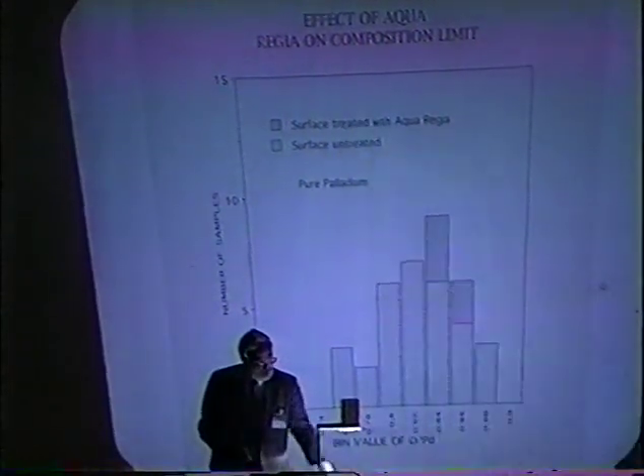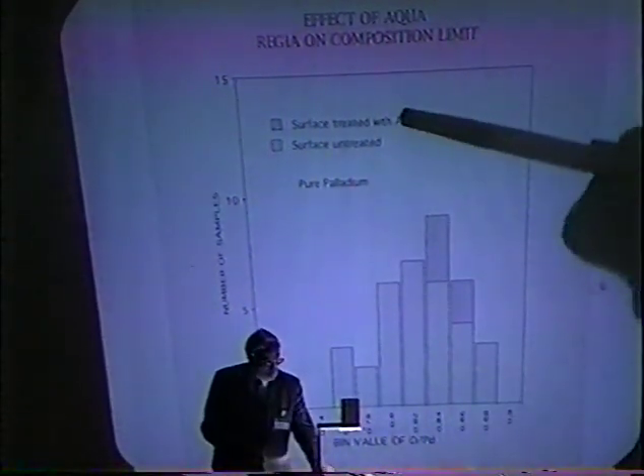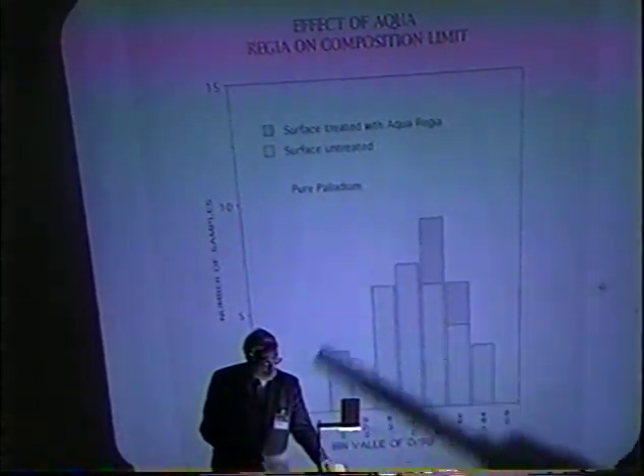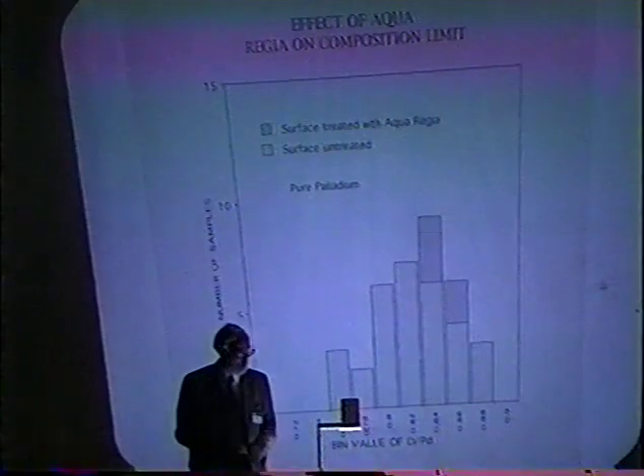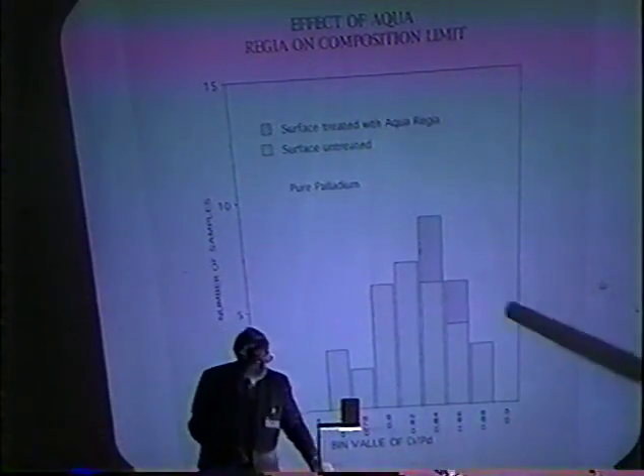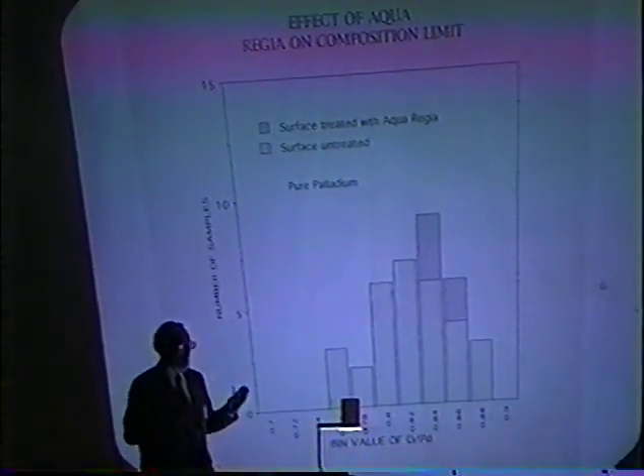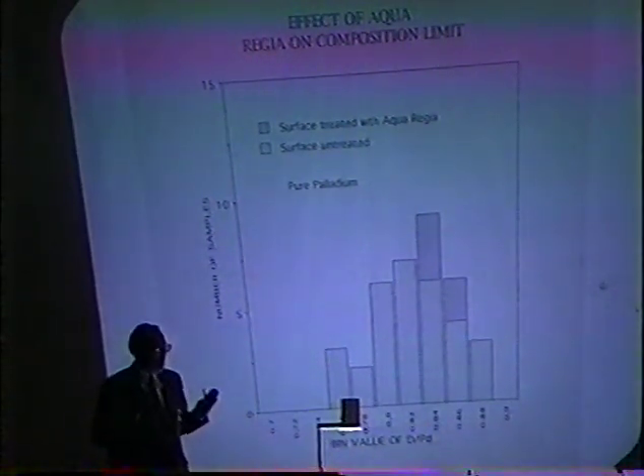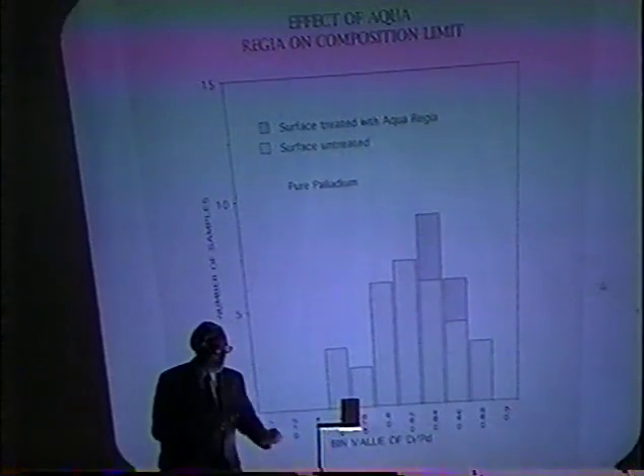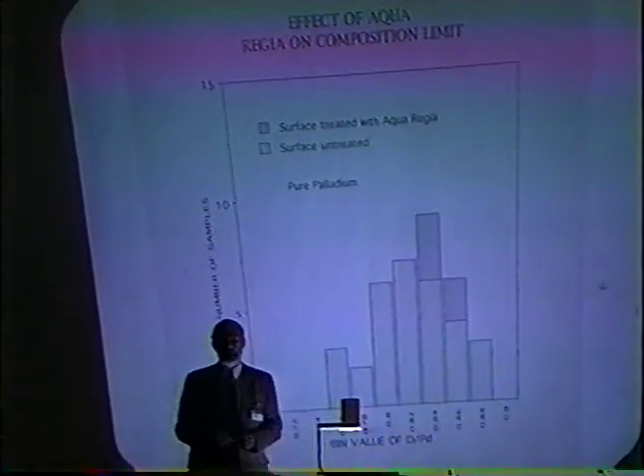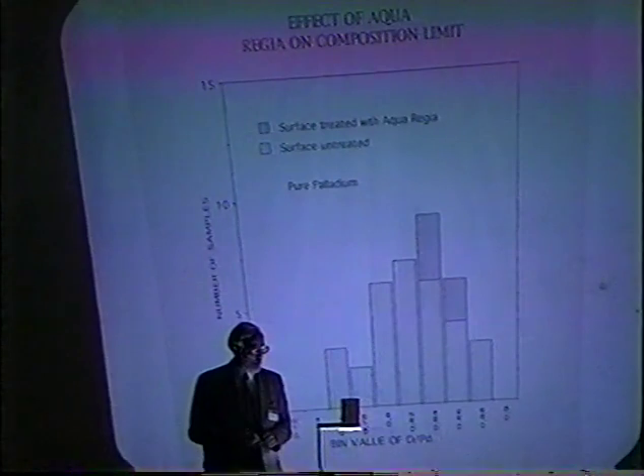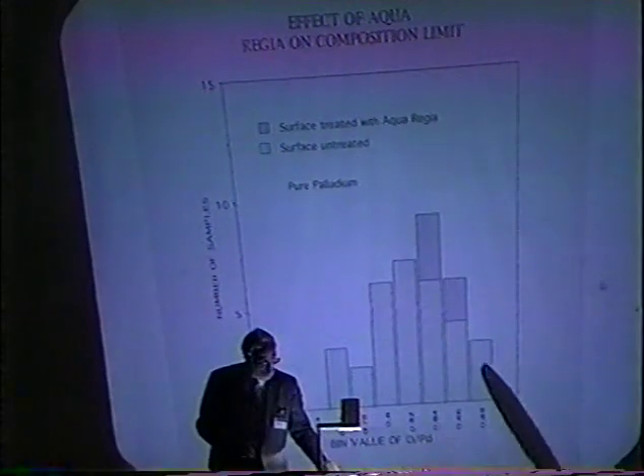I was able to use this material to compare the effect of aqua regia. These samples that are not colored were not treated with aqua regia. The aqua regia treatment tends to make the loading more predictable. That is, it brings it into a narrower range. And so it's beneficial in that sense. However, it clearly brought it down from what's available in the absence of aqua regia, but it brought it up also. So it works both ways.